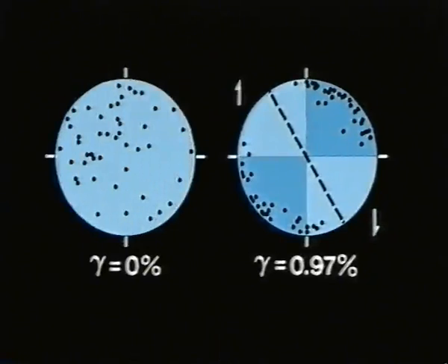It should be noted that in the center of the stereographic projection from the deformed sample there are few C-axes. Most cluster along the borders in a northeast-southwest quadrant. The peripheral concentration of C-axes suggests that grains in a high glide orientation have been eliminated during deformation. We have seen that the removal of such grains has been by processes involving dynamic recrystallization and grain boundary migration.